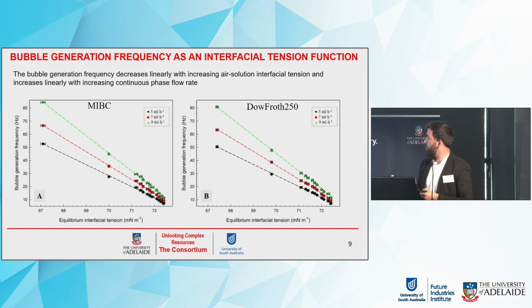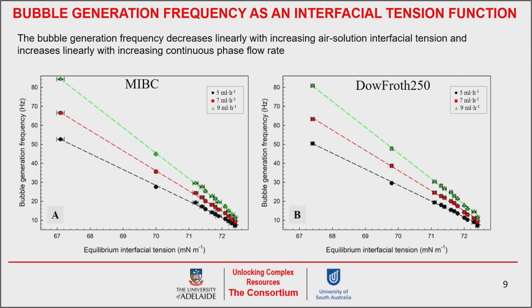So things are getting more interesting when we look at the interfacial tension and translate the bubble generation into the interfacial tension. And for both frothers, the bubble generation frequency increased linearly with decreasing interfacial tension, and the same dependency was observed for every tested continuous phase flow rate. And additionally, this sensing method based on the bubble generation frequency is very sensitive, as the drop of interfacial tension by 0.1 caused an increase in the bubble generation frequency of about 15%, which makes this method suitable for detection of even the smallest amount of the frother molecules in the solution.